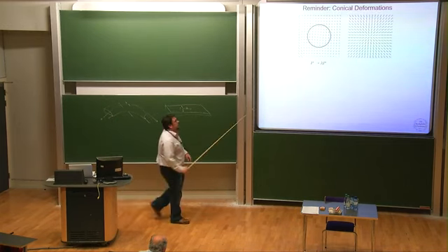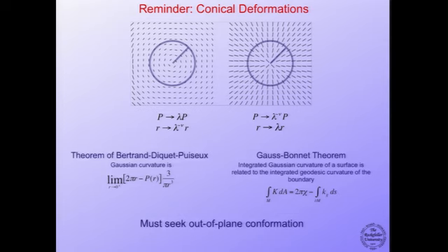So you look at the integral curve that lies tangent to the director field. Everywhere along this curve, this circle in the +1 disclination field, the material wants to shrink, right? It wants to get shorter because you're heating it and you're destroying the nematic order. Everywhere along a radius, the material wants to extend, right? And in the other version of the +1, things go oppositely, but we'll ignore that for the moment.